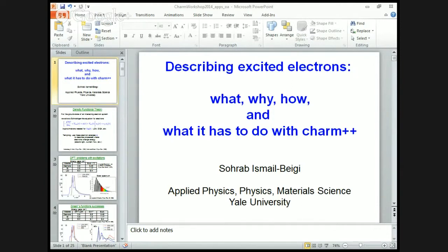The bulk of the solar energy is between a half and around 2 eV. Red starts around 2. So if you've never seen silicon and were a theorist doing ab initio predictions with electronic structure, you'd say, wow, silicon's going to be the best thing ever for solar, but you're way off, right? It actually starts absorbing strongly around 3 eV, which is already in the tail.